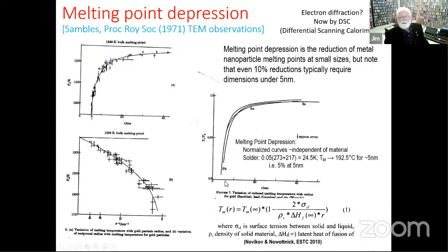And so a lot of times people will talk about melting point depression with particles of 100, 200 nanometers. And this is nonsense, because to get a 5% reduction, as a rule of thumb, for the melting point of, for example, some solder, to melt 25 degrees lower than the bulk would be to about this. These are figures for solder. So anyway, melting point depression is something that's well known.